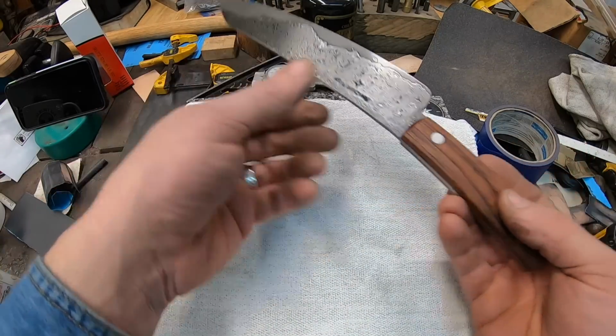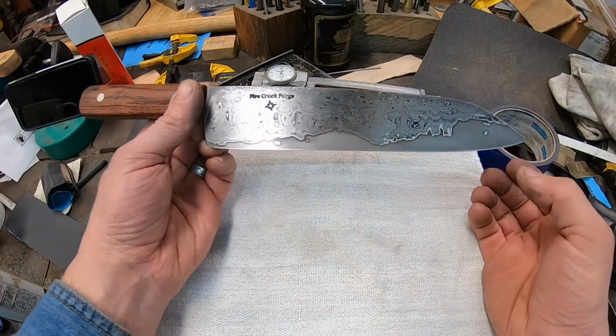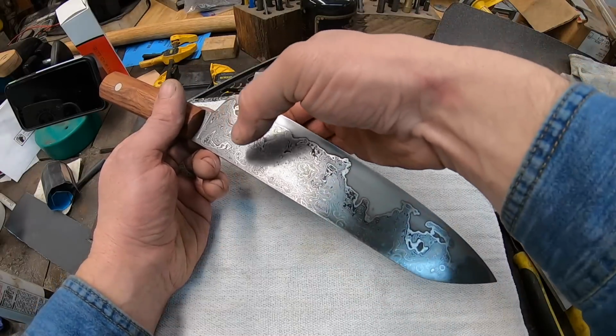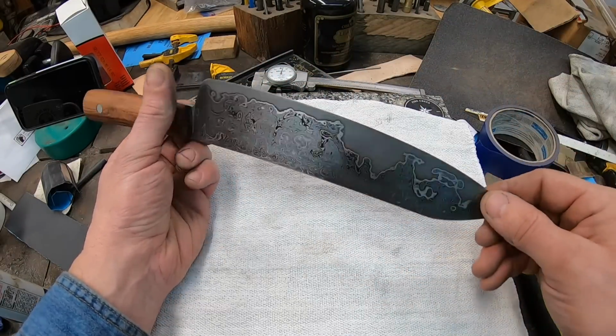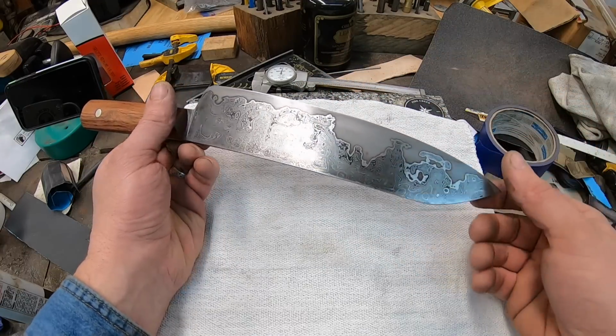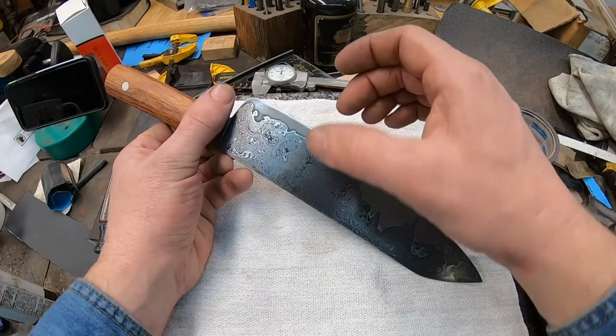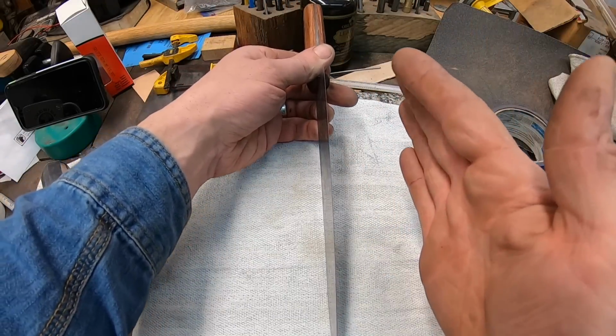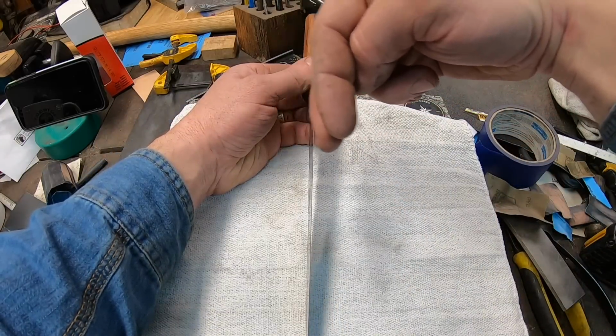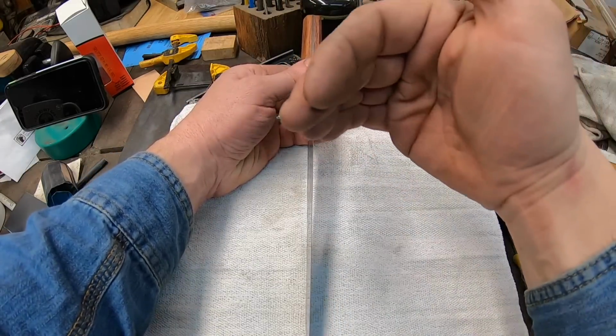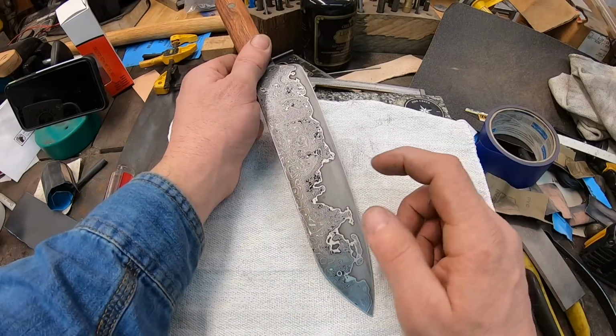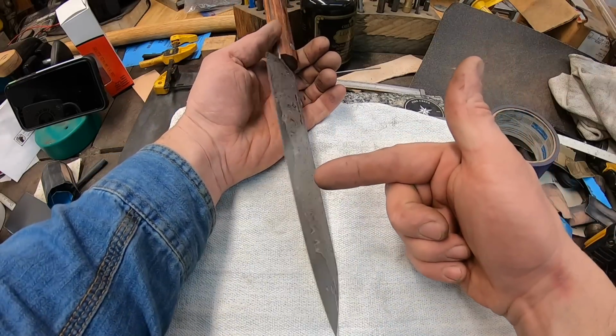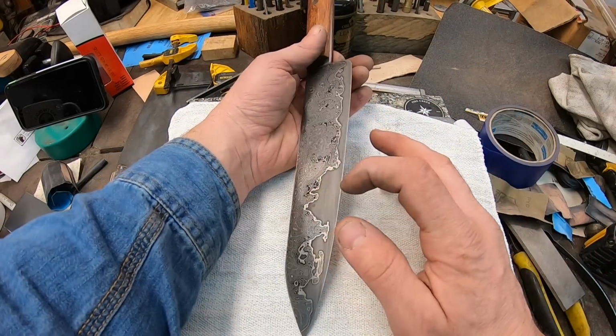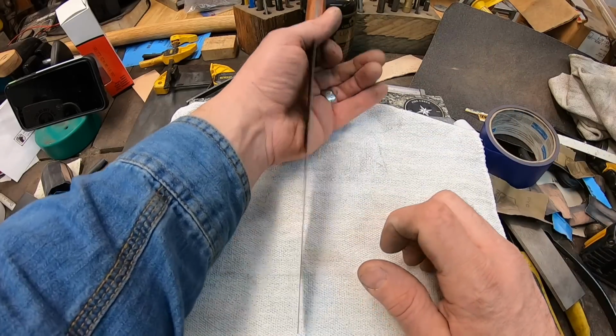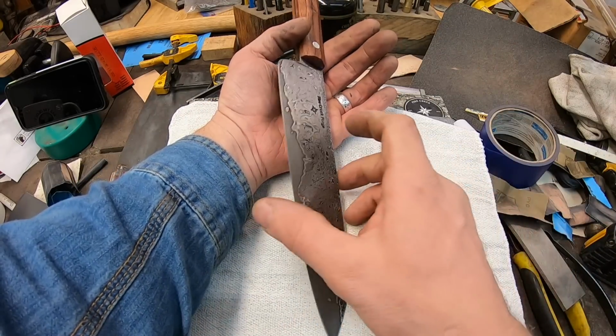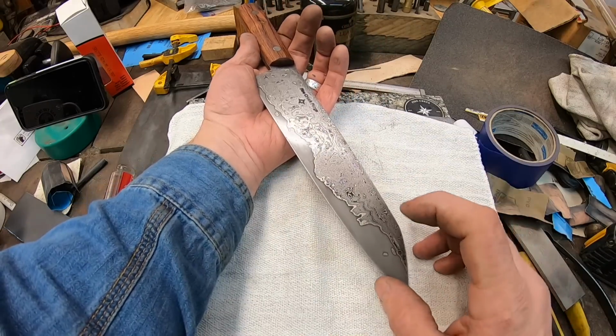All right, so basically what happened is when I forged this out, and this is after I got off the power hammer and finished forging the bevels in by hand, I did not evenly forge that by hand enough out here to provide that center steel a good even distance between each side. So I kind of pushed it over is what I'm trying to say. And you can verify that by noting that I pushed it over to this side in this particular spot. That's why when you grind it, it took off more of the cladding here and less of the cladding here. So it's a pretty telltale sign. And then similar on this and this here.